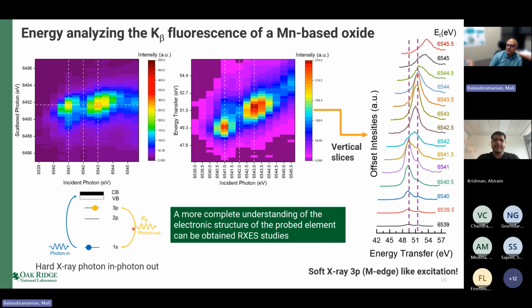Okay. Now, the example that I have shown here is K-beta fluorescence. So when you have K-beta fluorescence, you have the electron falling from a 3p to 1s level, and you're pumping the electron from this 1s level to this conduction band. The difference in energy between this photon in and photon out is deposited as energy into the excitation. And that can be shown here as the energy transfer. So for each pixel here, you have a corresponding pixel here. So it's essentially another way of plotting this data.